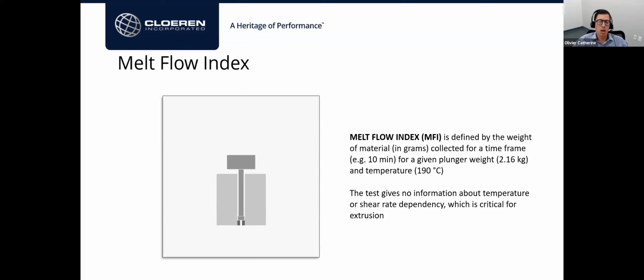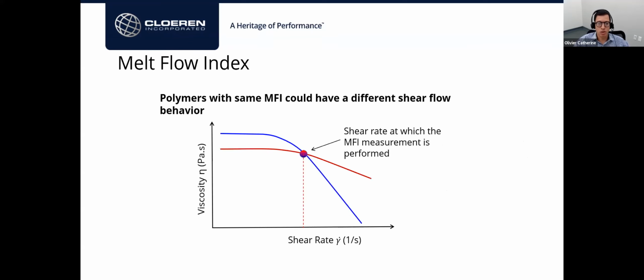However, it's an industry standard, and it's a simple way to quickly compare different polymers, or within the same family, let's say, and also to do some QC, for example. Although I think there are better ways to do that. This is an illustration to show that you could, in fact, be dealing with very different polymers with very different flow behavior and still have the same melt flow index value of 5 grams, for example, per 10 minutes.